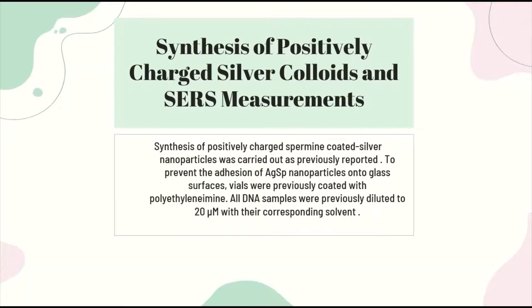Synthesis of positively charged silver colloids and SERS measurements: synthesis of positively charged spermine-coated silver nanoparticles (AgSp) was carried out as previously reported. To prevent the adhesion of AgSp nanoparticles onto glass surfaces, vials were previously coated with polyethylenimine. All DNA samples were previously diluted to 20 µM with their corresponding solvent.